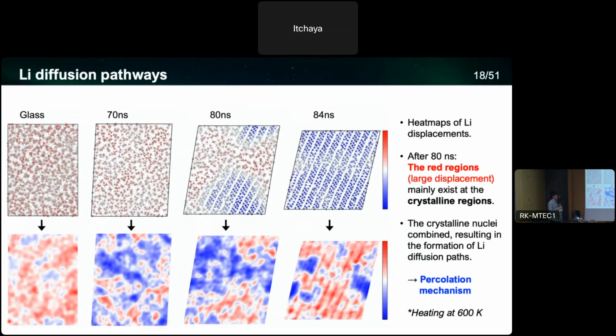So what we obtained is quite similar to the experimental observations. And now we want to know where the lithium migration path is when we have some crystallized regions. To know that, we plot the heat map of lithium displacement during the MD simulations. Here we show four cases: glass, 70 nanosecond before the crystallization, the middle of crystallization, and almost the last part of the crystallization. And the heat maps of lithium displacement are shown in the lower panels.